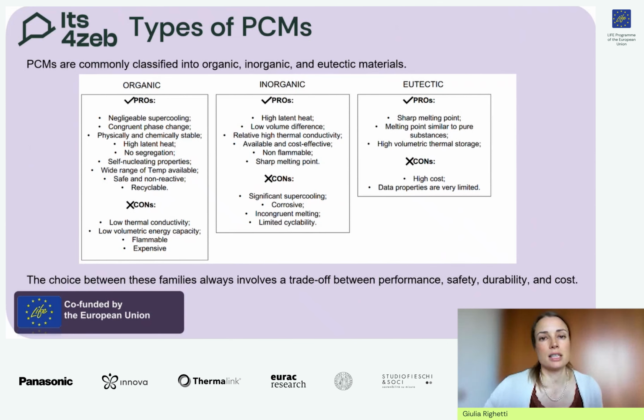So we have to select a phase change material. Usually, phase change materials are classified into 3 categories: organic, inorganic, and eutectic. Organic, such as paraffins, are chemically stable and show very little supercooling, but on the contrary, they have a very low thermal conductivity and sometimes they are flammable. We move to inorganic, the second group, such as salt hydrates. They offer relatively high thermal conductivity with respect to organic, high latent heat, and good volumetric density, but on the contrary, they suffer from a lot of supercooling, they are corrosive, and they are not very stable in time, so cycle after cycle.